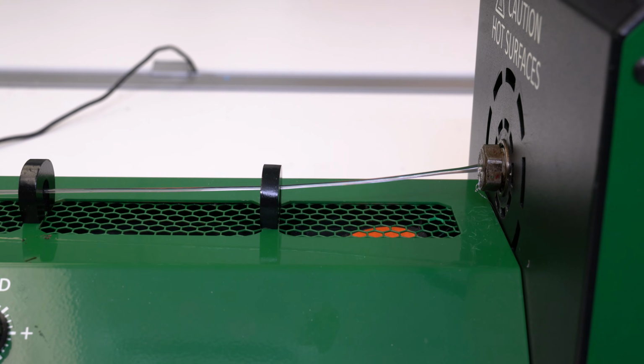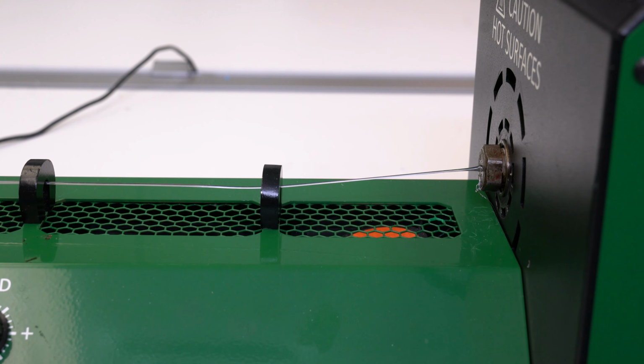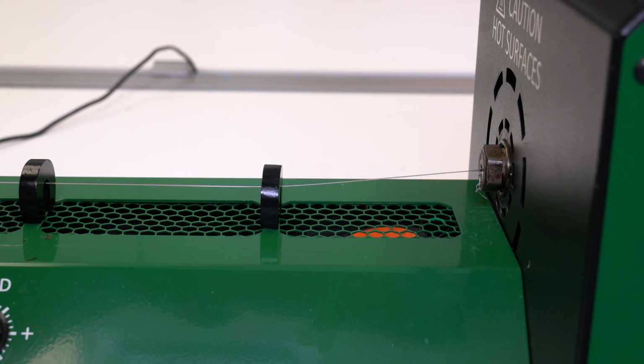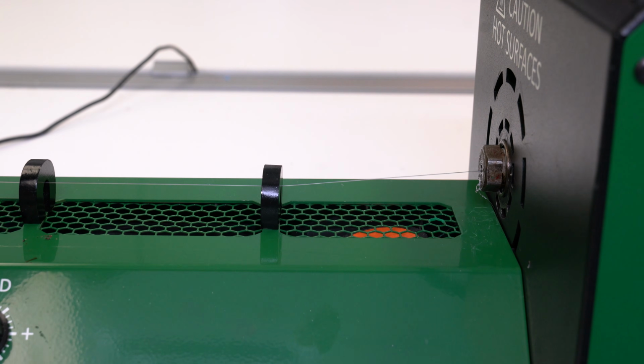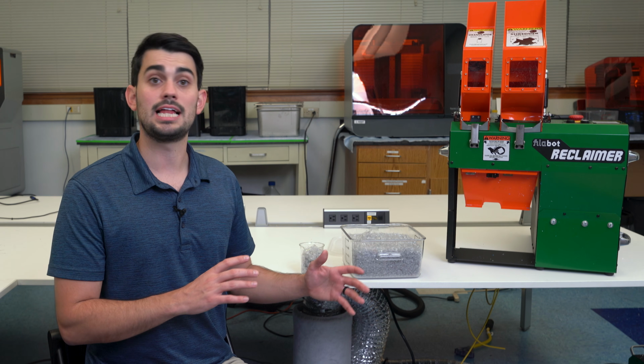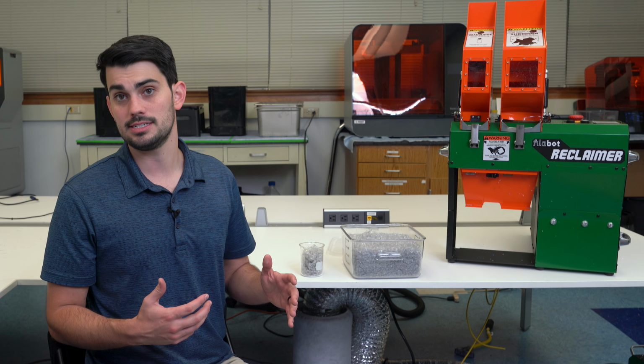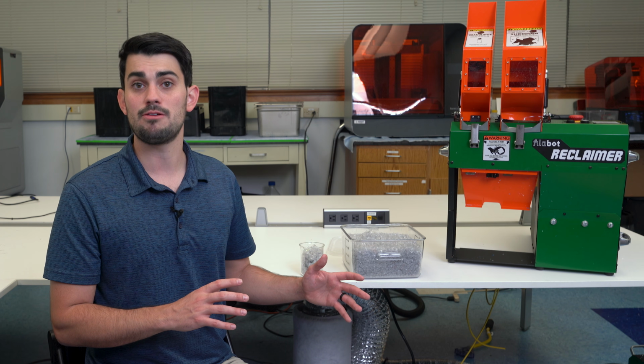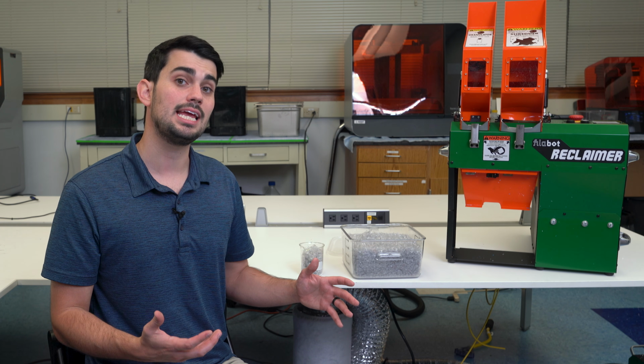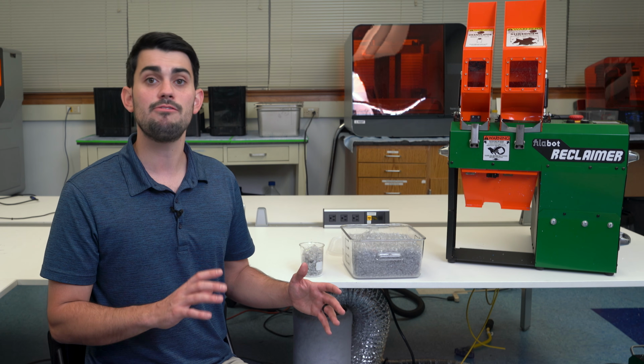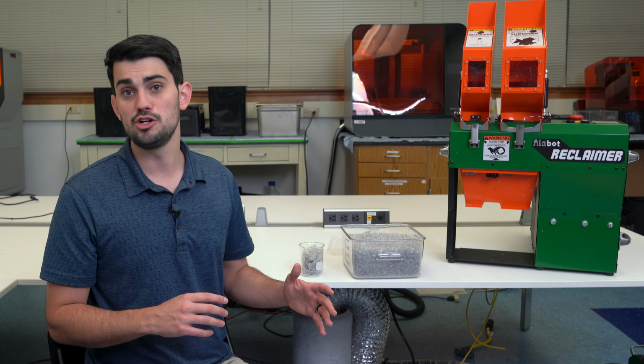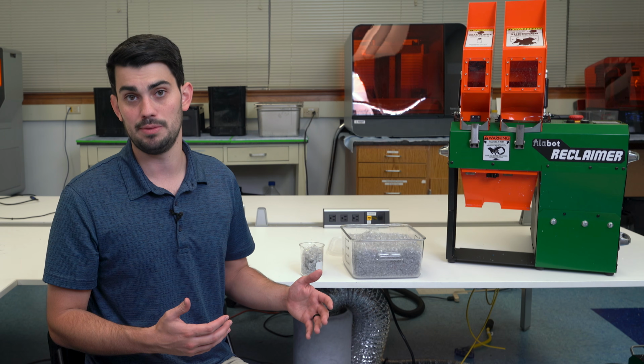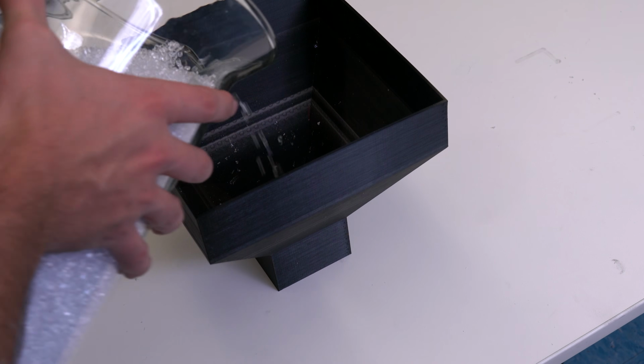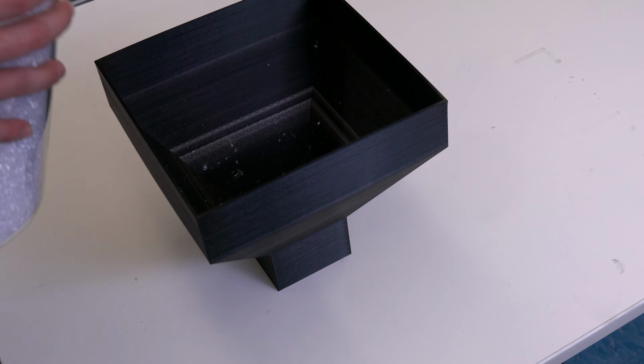If the extruder doesn't receive a constant amount of material entering to match what is leaving, the output will be variable, which can cause inconsistent filament diameter or even cause the filament to break at the die when the spooler pulls on it. Some shapes are more likely to plug in the hopper or feed port than others. We didn't talk about it earlier because the regrind from the 3D printed parts had enough flowability as to not be a problem. However, thin film scraps or flakes that are produced from recycling most plastic containers, such as water bottles, have terrible flowability.